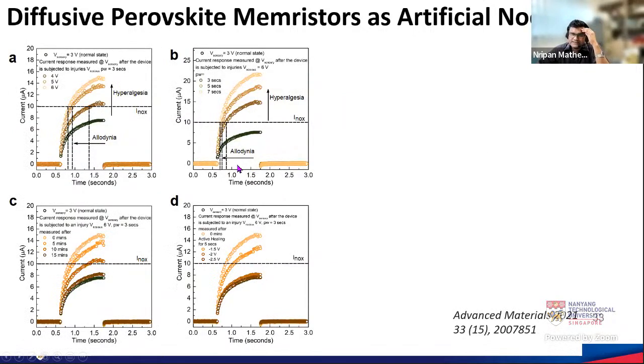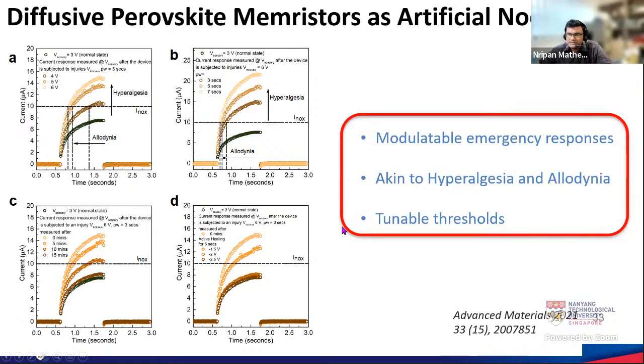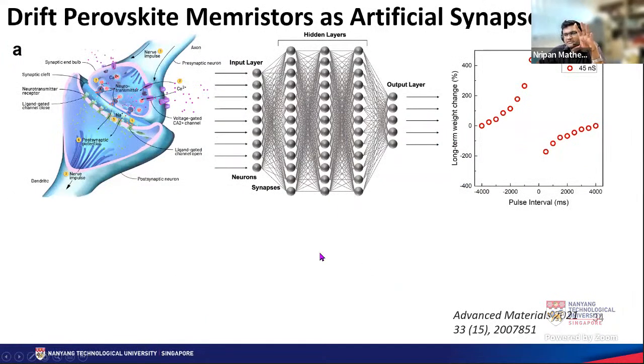But there are also other characteristics such as allodynia and hyperalgesia. For example, when our hand is damaged, or let's say we have had a fall, even a gentle touch can trigger pain, right? That is because we are sensitive at that moment. So allodynia is when pain occurs to a stimulus that normally does not evoke pain. These kinds of characteristics could also be seen by our devices. Essentially there is a tunable threshold when it is damaged that shows all these kinds of behavior. And of course, this is for the PEDOT:PSS based perovskite devices. The nickel oxide based perovskite device acts more like a conventional synapse, and you can again show STDP characteristics, etc.